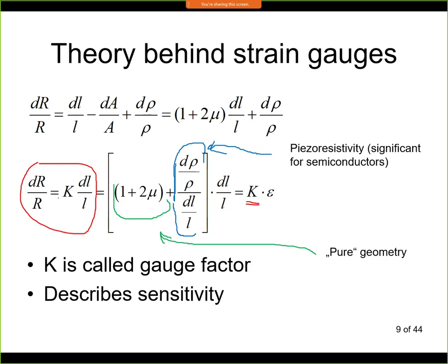The reason why we have separated this into 2 parts is the following. The pure geometry is the dominant factor for metallic strain gauges, and the piezo-resistivity is the dominant factor for the semiconductor strain gauges. So for semiconductor strain gauges, the majority of the change from the applied strain will be created by changes of resistivity here, and only a very little part will be the pure geometry. But for metallic strain gauges, this part of the equation is very small, negligible, and this part is very large.